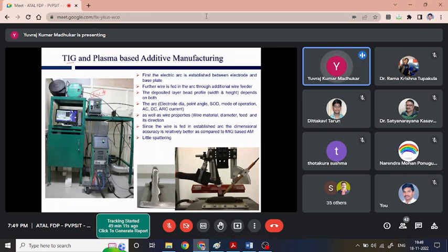What is the push-pull mechanism? Basically, if I zoom in on this area, in a TIG-based additive manufacturing process, we generate the stabilized arc on the base plate and we feed the wire into this stabilized arc. Once the deposition is done at the edge, we have to make sure the wire is pulled back from the arc zone before the arc turns off. Otherwise, this wire is going to get stuck to the deposited bead itself.